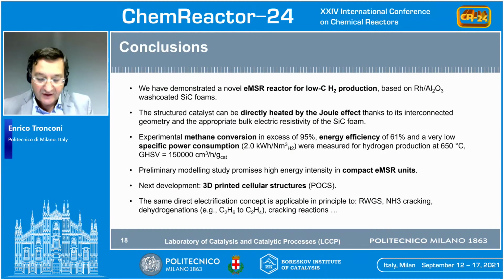So coming to the conclusions, in summary, hopefully we have been able to demonstrate experimentally the feasibility of running the methane steam reforming reaction over a Joule-heated wash-coated foam catalyst. And the initial performances that we have been observing in our lab scale setup promise high hydrogen productivities, high energy efficiency, and low specific power consumptions, thanks to the transport properties of the foams. And these data also, according to the modeling results, seem promising in view of compact electrified reformers for distributed small-scale applications.